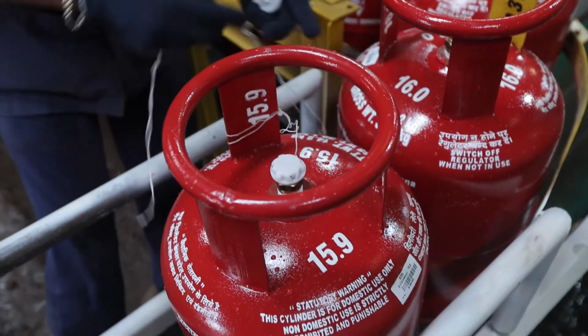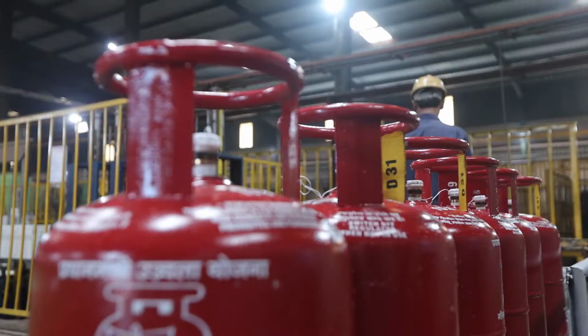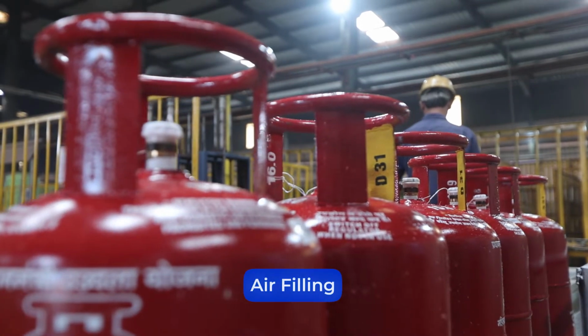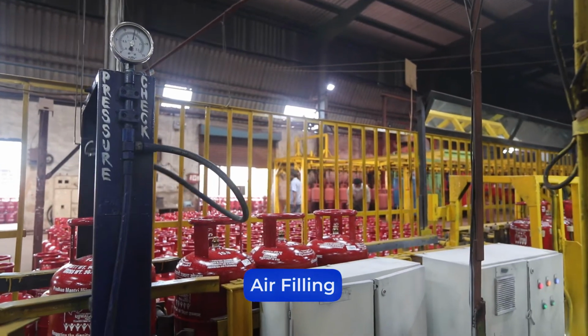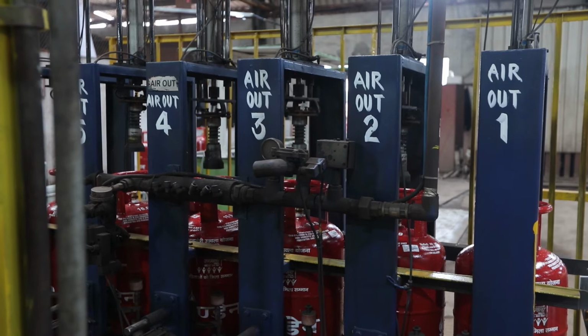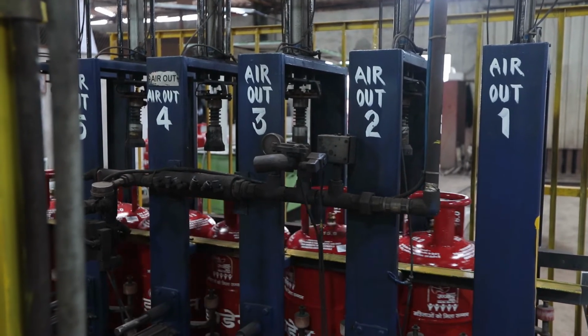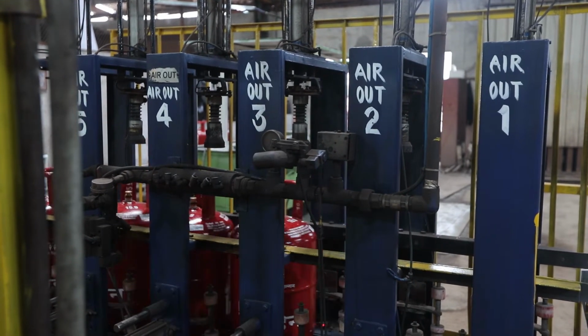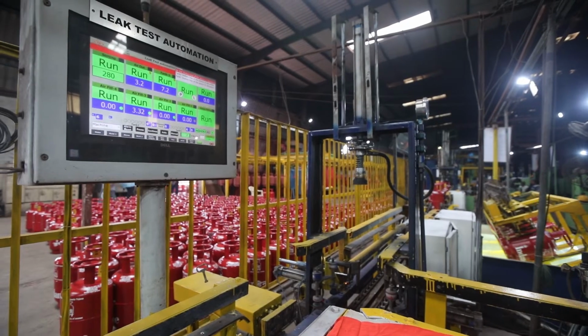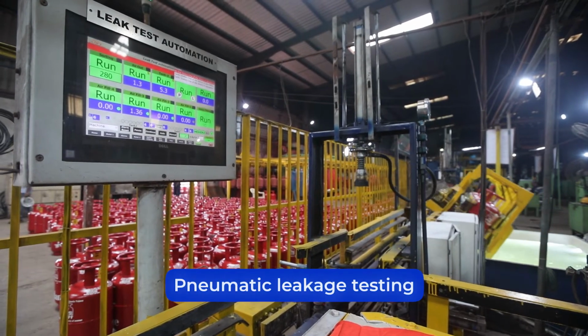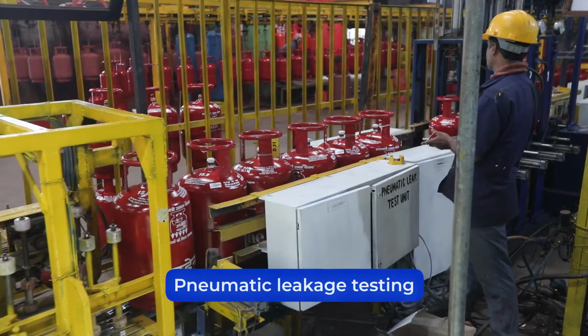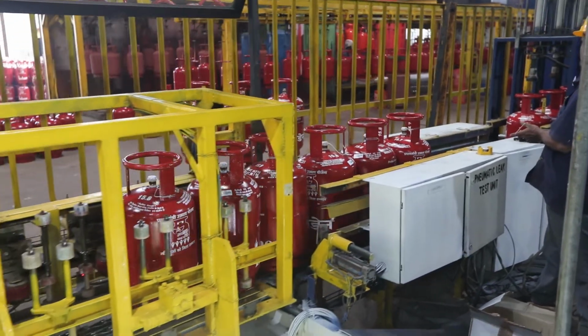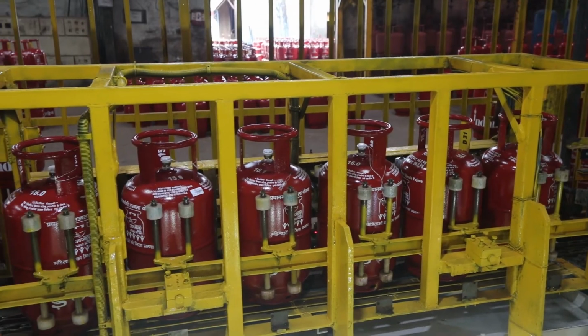After the SC valve fitting, refrigerated compressed dry air is filled with a filling adapter. During this process, air pressure in the cylinder is kept at 12 kg force per square centimeter. And after the air is filled, cylinders get ready for pneumatic leakage testing. Now comes the pneumatic leakage testing.